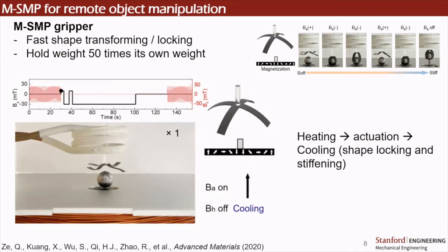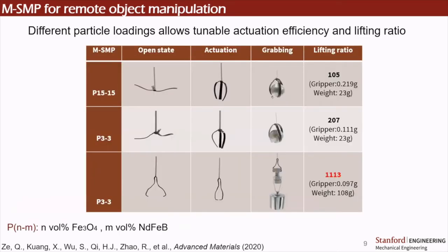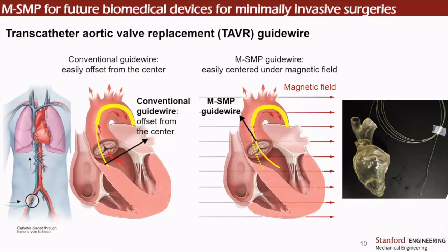So basically we developed a robust soft gripper that can tune its rigidity to interact with the object. By tuning the particle concentration in the soft composite, we could develop very, very small grippers that can grab something over 1,000 times their own weight. For the potential biomedical application of this material, we are always looking at whether we can use these different technologies that we develop for minimally invasive or even non-invasive operations.